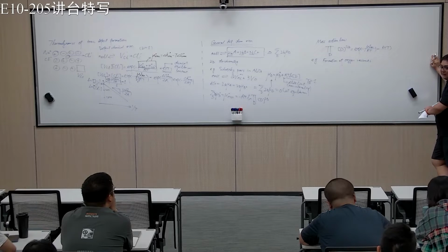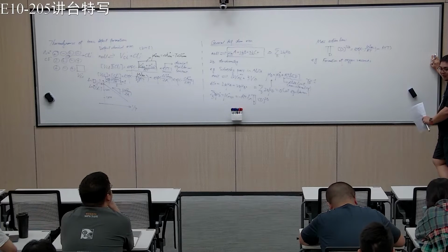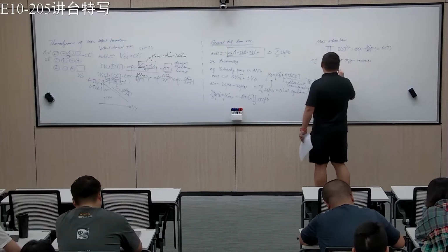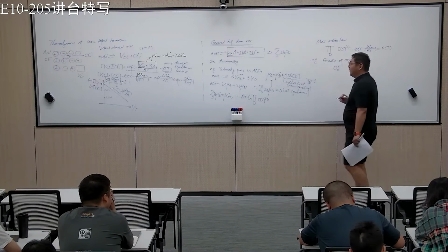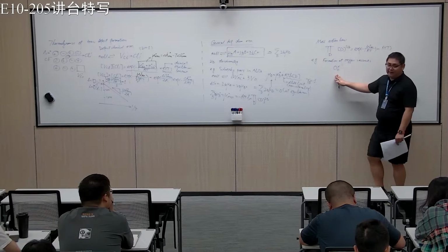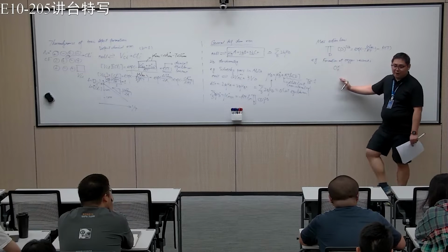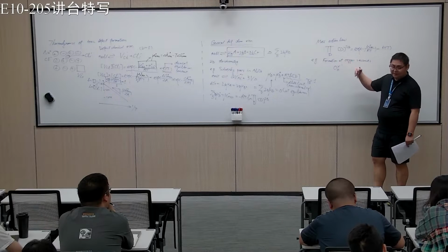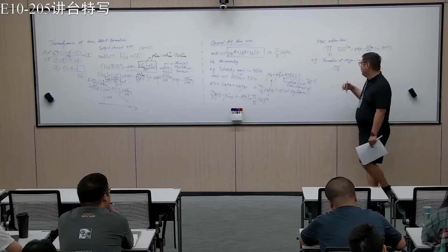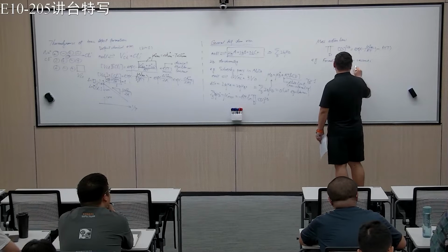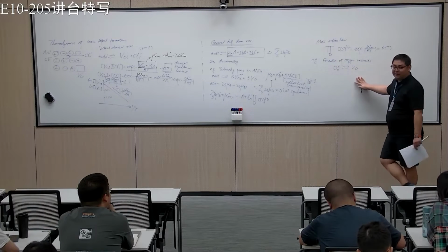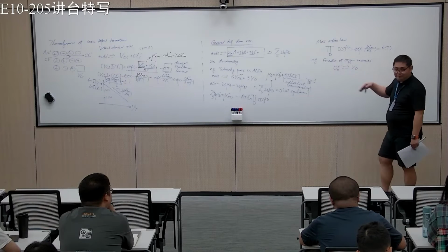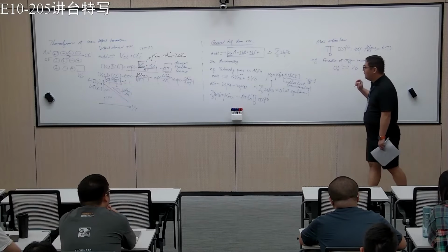So if we just think of only oxygen vacancies and there's no other ionic defect, then usually what we write is something like this. So basically we have oxygen sitting in oxygen site, right? So it's just normal oxygen. So of course oxygen sitting on oxygen site, there's no difference in charge, right? This is a normal oxygen. Then we can form oxygen vacancy. Oxygen vacancy has two positive charge, right? So if we have two positive charge, we have to charge balance it, right?